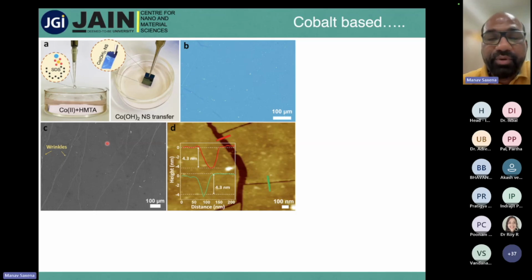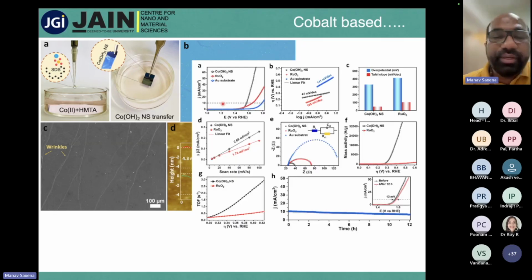Based on the AFM, the thickness of the sheet is around 4.3 nanometers, which is quite thin, and it has a large area. This is very beneficial over hydrothermal synthesis, where we cannot achieve a large area, even a millimeter square. Here we are achieving centimeter square films. It also shows OER application in basic media, and it is on par with the standard OER catalyst, ruthenium oxide, in basic media.